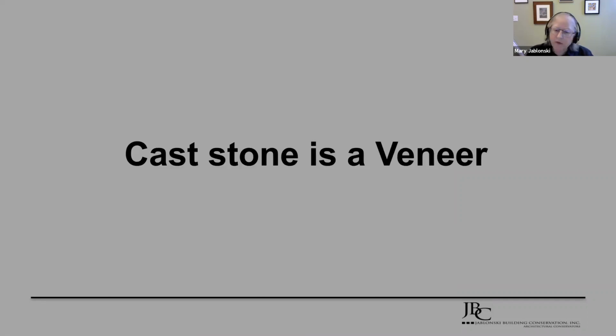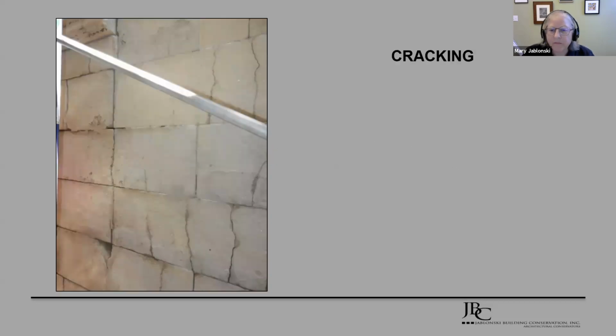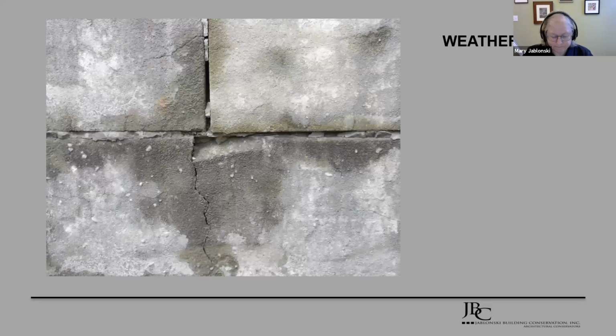It was soon apparent that the cast stone was a veneer, but we didn't know how it was attached to the backup wall. And the demolition occurring at the top of the building as we were surveying didn't add to our comfort. We found a few masonry anchors, but most of them were rusted or in poor condition. We found significant cracks, including hairline cracks everywhere. There was a lot of weathering due to wind, rain, snow, pollution, acid rain, and even salt water. Don't forget, New York City's not far from the ocean. There was erosion of cement paste, exposure of aggregate particles, and a loss of crisp edges.